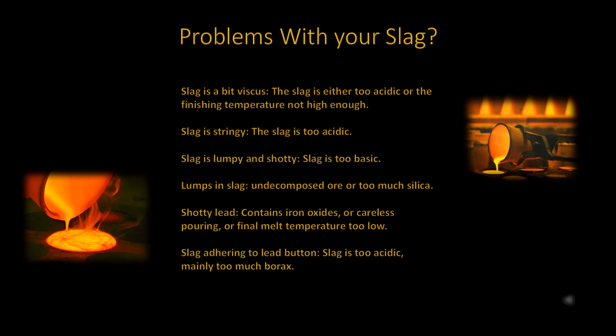During pouring, if it was noticed that there were lumps in the slag and the slag was fluid, the indication is that there was undecomposed ore sample in the slag. Now this may not be noticed. It is best to check the slag when cooled. If the lumps were undecomposed ore, then an increase of acidic flux would be required for decomposition. However, if the lumps found were actually undecomposed silica, then the acidic flux would need to be decreased.